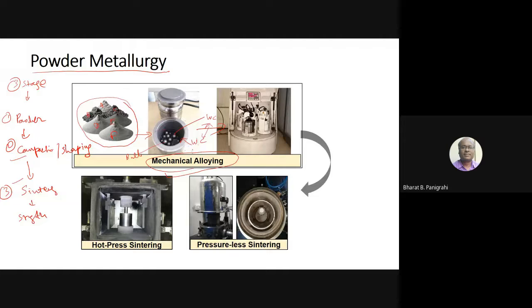Okay, so this can be alloyed after a few hours, 10 hours, 20 hours, 15 hours. You will see that these independent elements, what you have seen, convert to a particular alloy. So this is the step of mechanical alloying. Powder is produced. Then you can go for sintering.